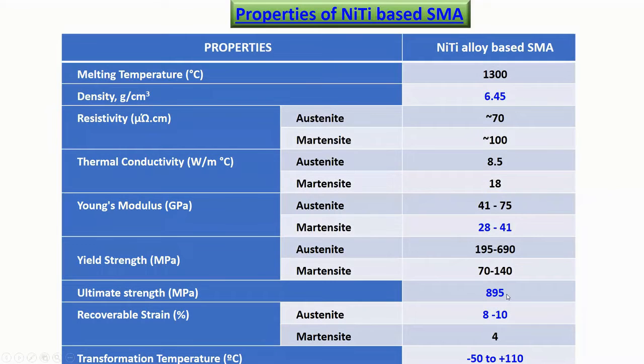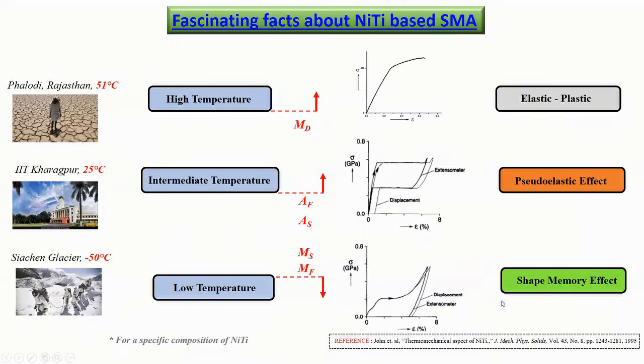Once again, the ultimate tensile strength is high, the recoverable strain is high, and so on. So with this, let's look into the typical stress strain diagram of the nickel titanium based SMA. These are some of the fascinating things that we can see: at high temperature, this material can behave like a regular elastic plastic material. It has some elastic deformation, following which there is some permanent deformation.